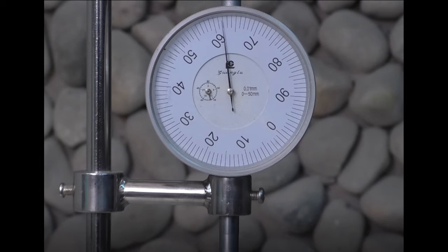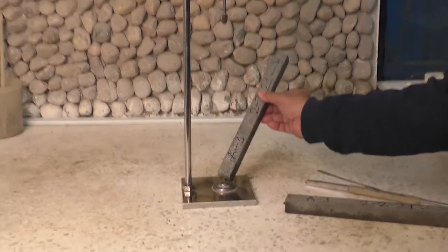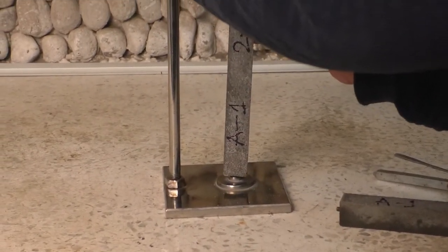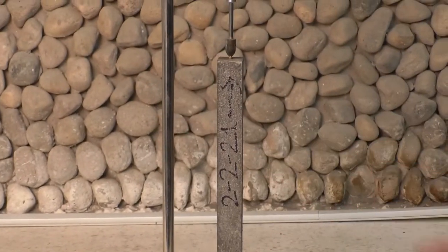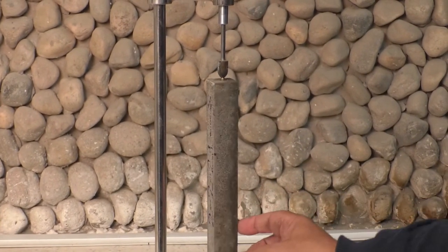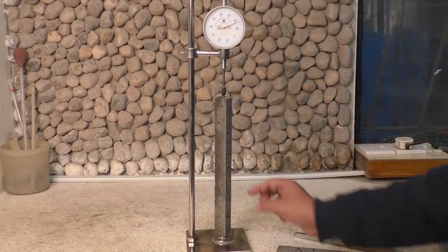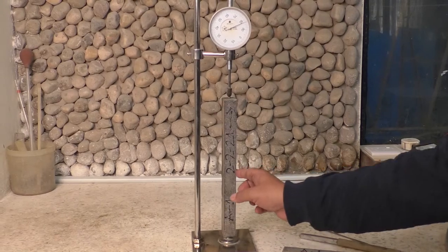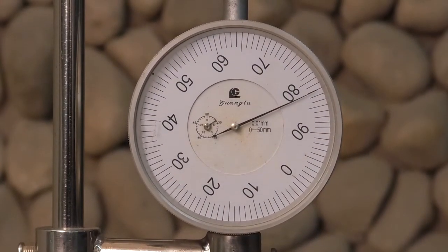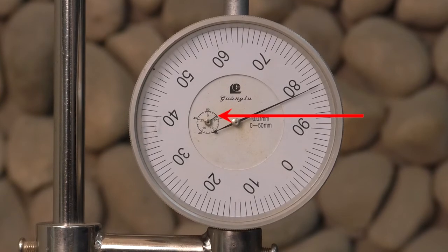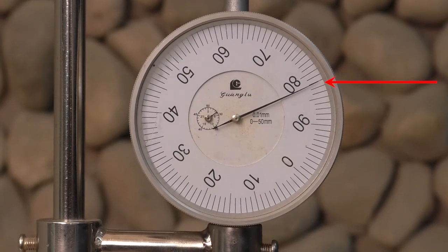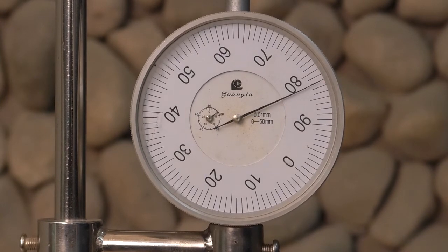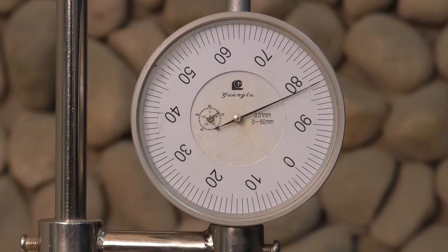We have to repeat this for the 14 days test because temperature change can cause differences in this length measurement. We are now making the first reading at the age of 24 hours from the time of mixing. We have to rotate the sample several times to observe if there is any change in the dial before taking the first reading. As you can see from the video, in the small dial the reading is 3 and in the large dial the reading is 82. So, the total reading will be 3.82.